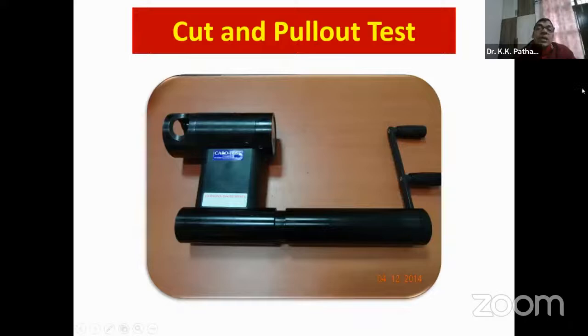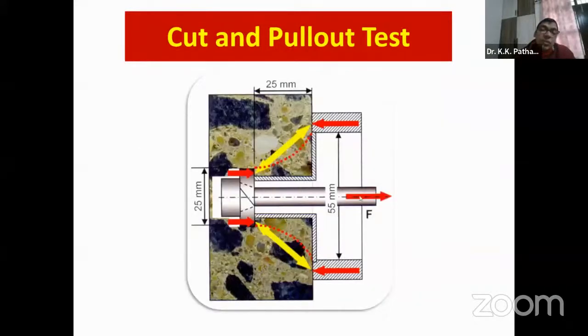This is a very latest test we call the cut and pull out test. It is very accurate, and here we get a very good value of the strength of the concrete. Basically here we do the pull out, and pull out is supposed to be the best way to get the strength of the concrete. But this is a very costly affair. It takes about 2,000 per test. That's why we don't recommend it much. But if there is a specialized case, then we go in for this type of testing.